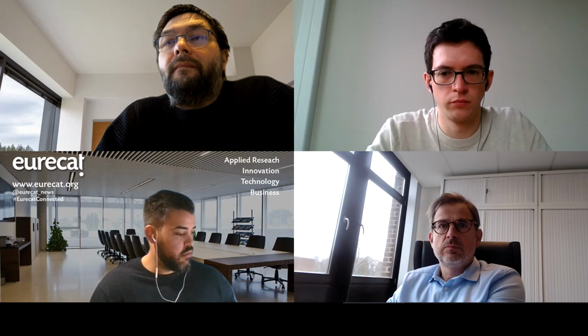Thank you. And maybe just a specific question for Antoine. The work that you showed is based on notched specimens. So they are not fatigue pre-cracked, or it's just an EDM notch? It's an EDM notch, and then it's pre-cracked by a razor blade. By razor blade. Yeah, you sharpen the crack by using a razor blade, making a sharper crack to be sure that your initial defect is smaller than the critical opening, as David showed in the beginning.